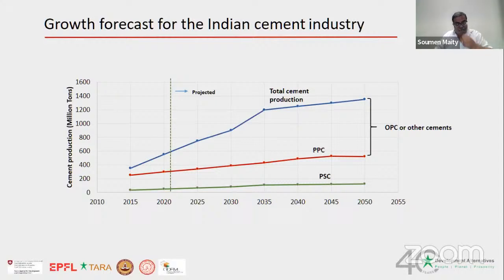Now, this is the growth forecast based on the projections that we did for consumption of fly ash by the cement industry, if we don't have enough fly ash. PSC slag cement, because slag is not much, is going to remain at 9%. PPC again will be a stagnant growth because you don't have enough fly ash. But if we have to meet the growing cement demand, then till date, I'm not talking about LC3, we don't have any other thing other than falling back into OPC. And if we fall back into OPC, that means your CO2 emissions, as Professor Gettu already mentioned, 910 kg of CO2 per ton of cement. So the emission factor increases like anything.